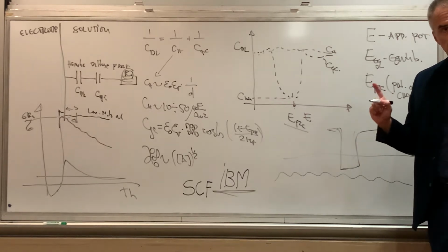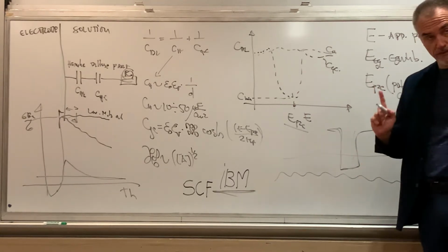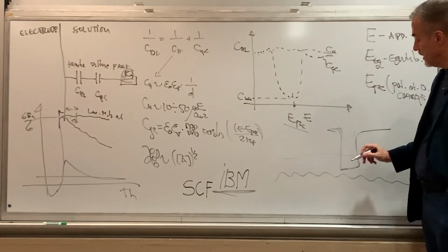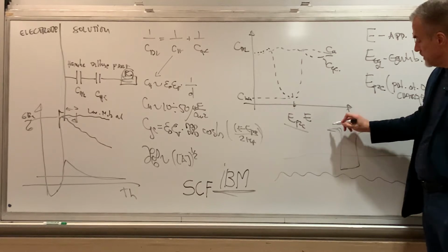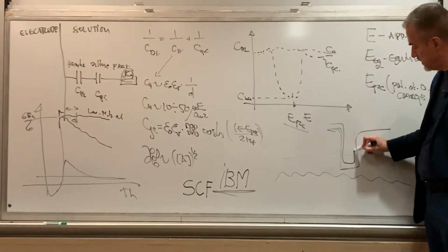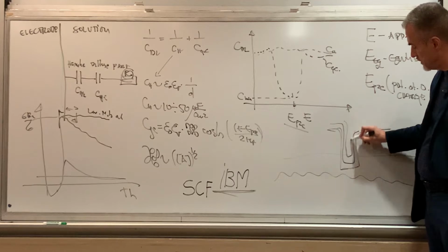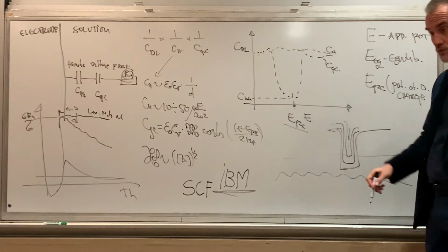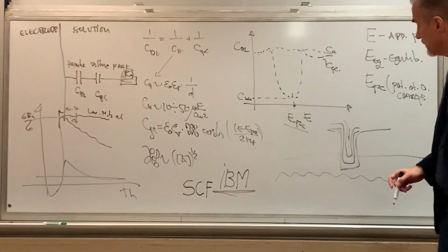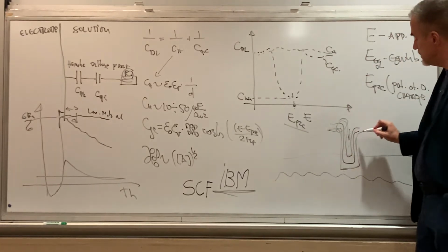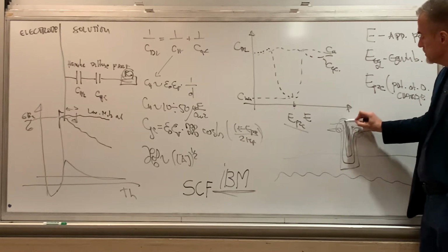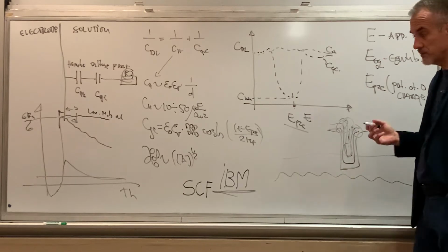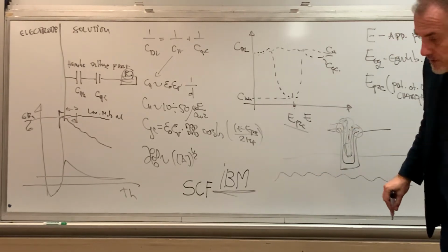And you have a specific design of the chemical bath, which is very important for you to understand, meaning specific additives, etc. When you start plating, instead of getting conformal growth, eventually looking like this, and eventually closes here before it fills this, which you would expect from electrodeposition? Or maybe get these edges growing faster due to the field concentration and close this with a void inside, which is something to expect from the physics of the field distribution.